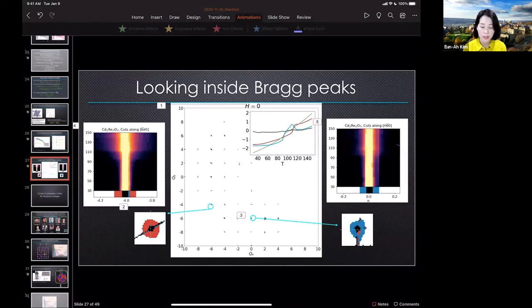Now, as far as I am concerned, what I can say with confidence is that we found very unusual diffuse scattering behavior that is sustained over a wide range of temperature in a phase, and it goes away when you leave that phase. That's what I'm confident about. My best explanation at the moment is that this seems most consistent with Goldstone mode fluctuation. We also see critical scattering, but we know what critical fluctuation looks like. This is an interesting fluctuation phenomenon.